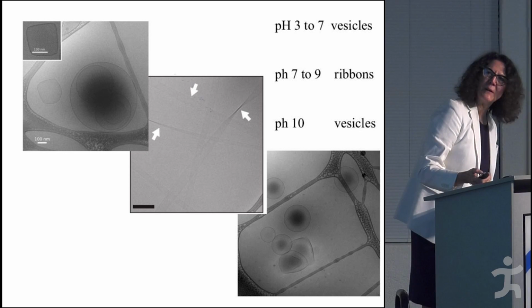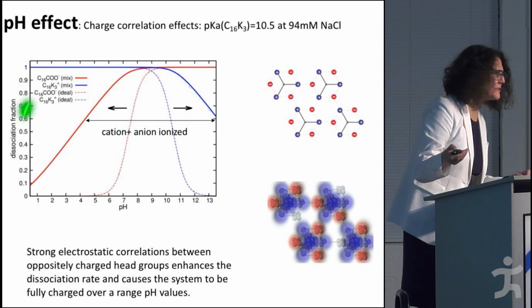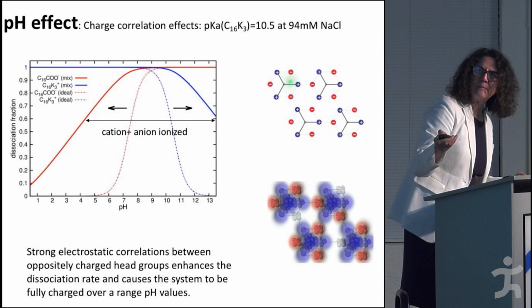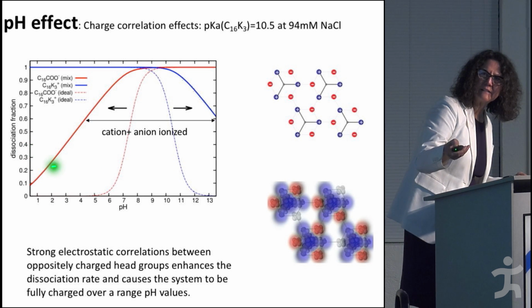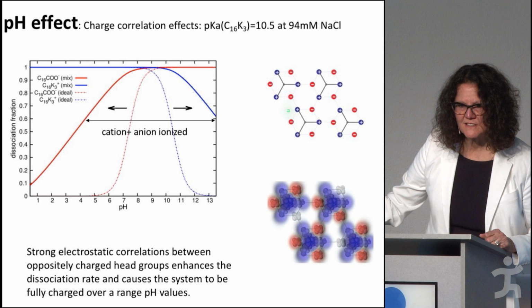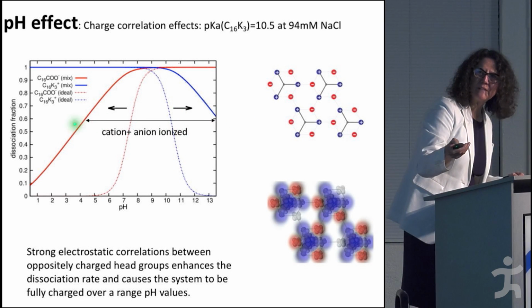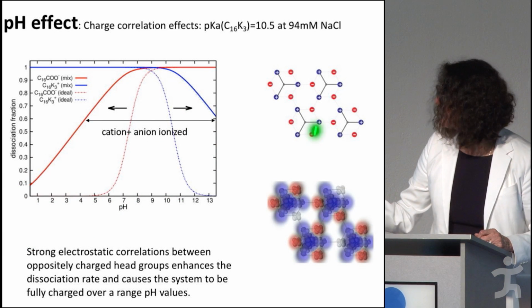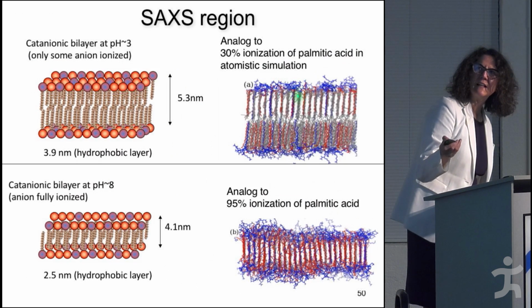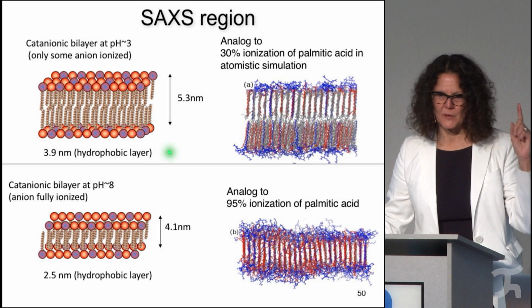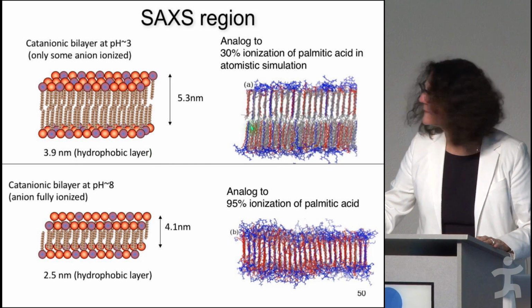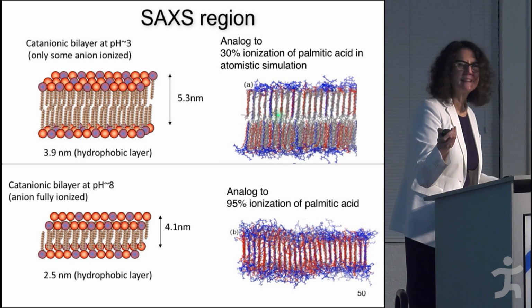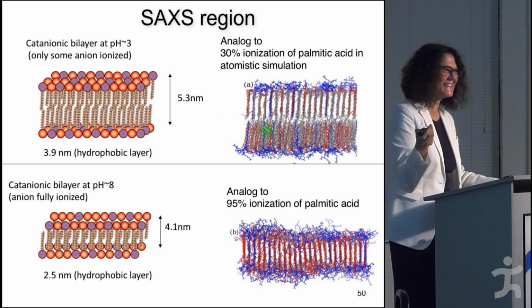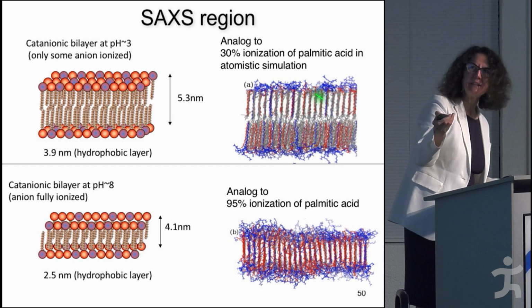So what I was trying to explain is that the pH gives you the fraction of the dissociated charge of the molecules. Here, the blues are the positively charged, and the red are the negatively charged. When you mix them, you can see that at pH 3, only around 30% of these are charged, and 70% are not charged. Okay? And so this tells you the fraction at the different pH of the blue and the red. So we assemble them, for example, at pH 3. So 70% of the ones that had -1 are uncharged. I call them here in color green. No, I'm sorry, gray. There's no green there, sorry. And the ones that are charged are the blue and red, the 3+ and -1.